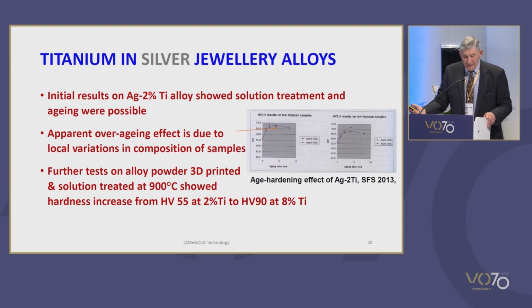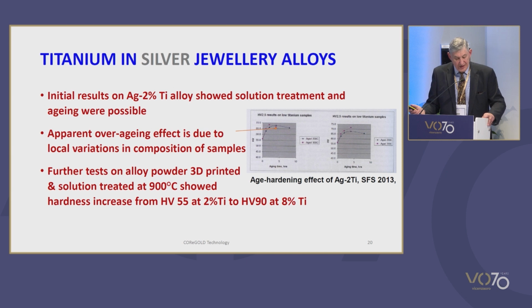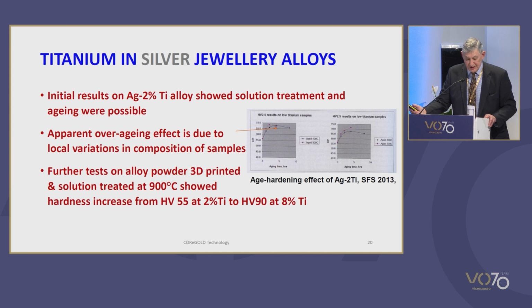Some initial tests on wire made in a silver 2% titanium alloy from a casting sprue indicated that solution treatment and age hardening were possible. The figure gives some results on samples solutionized for 2 hours at 800, quenched and aged. Wright cautioned that the apparent overaging effect is possibly due to local variations in composition in the samples. Further tests on samples made by 3D printing from alloy powder and solution treated at 900 shows a steady increase in hardness with titanium content in the range of 2 to 8%, with a hardness varying from 55 Vickers at 2% titanium to greater than 90 Vickers at 8% titanium in the solution-treated condition.